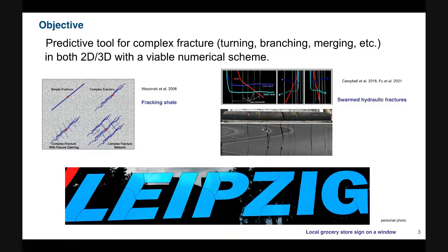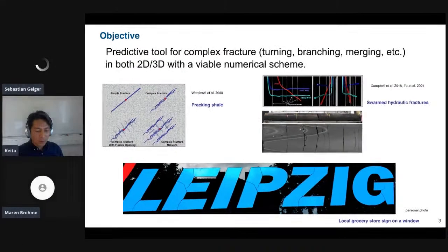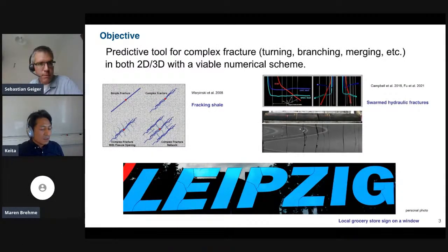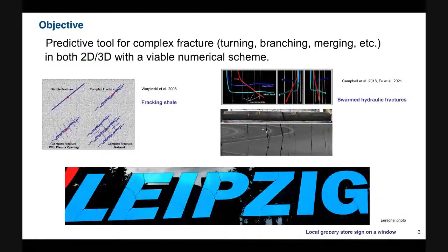And then those letters cracked, probably under some loadings, most likely the thermal expansion of the window. But notice that there are no cracks in letters I, because letter I's don't have any stress concentration. And the cracks initiated from the stress concentrations in other letters.